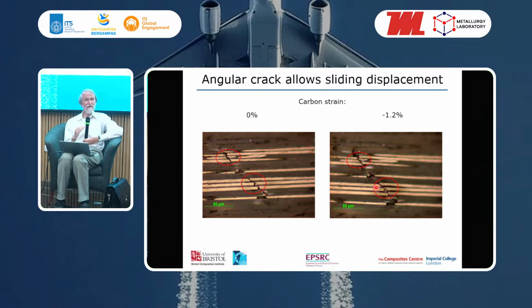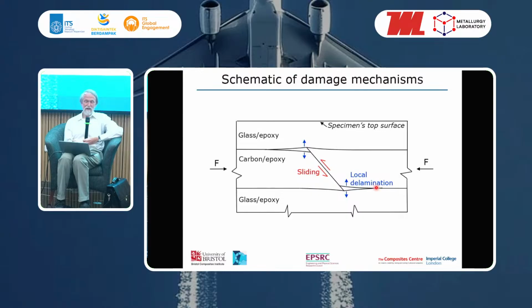Because of the angled crack under compression, there's a wedging action which opens up the crack. You can see this better on this schematic. Here we've got the glass, the carbon between the glass plies. The carbon fiber ply has failed with multiple failures at an angle, roughly 45 degrees in many cases. And then there's a wedging action which causes some local delamination to occur there. This produces some additional strain, which is what gives us this pseudo-ductility in compression.